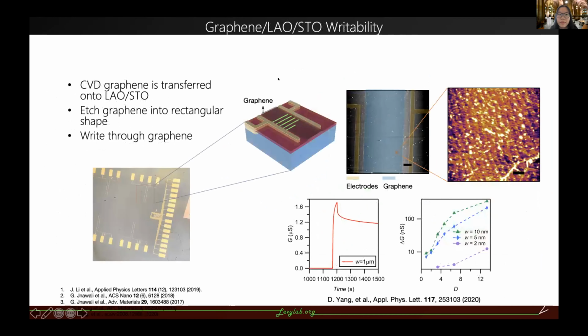And this is, as I mentioned, we have graphene on top of LAO/STO. Here it shows we transferred the CVD graphene onto the LAO/STO using wet transfer. And this is the AFM over the graphene, and we can still see the terraces of the STO, which shows the graphene quality. And by exposing this nanowire, we can see a clear conductance jump from this writing process, which shows we can create nanostructures at the LAO/STO interface underneath the graphene.